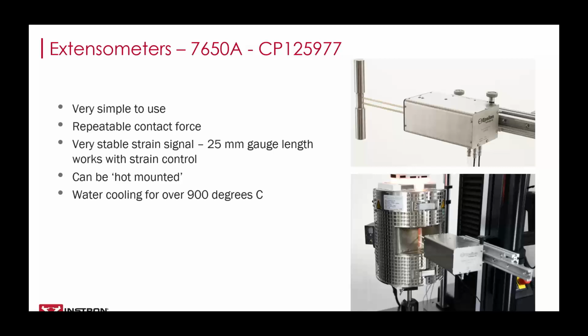And lastly, we have the 7650A extensometer. This one is suitable for ASTM E21, as well as ISO 6892-2 for strain control in both 50 millimeter and 25 millimeter gauge lengths. So a quick review on the extensometers we discussed. If you're only testing to ASTM E21 with a 50 millimeter gauge length and strain control, or if you're using crosshead control, then the cold mounted E3448 extensometer is a great cost-effective solution.